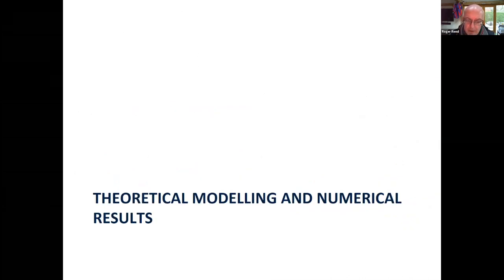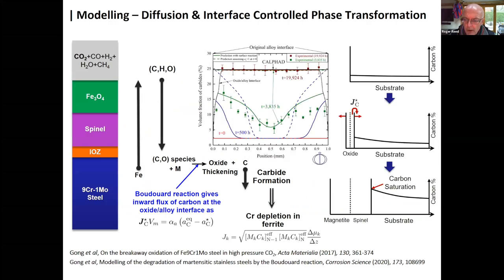Okay, so now I'm going to say something about some of the details of the theoretical model that we have put together for this project. So I'd like to start by just pointing out, of course, this is quite complex. You have a 9-chrome molybdenum steel, you have a spinel, and then a magnetite-based iron-rich spinel on top. Then you have this gas, which, of course, is quite complicated in its composition. And then we have a zone here where we have the interfacial reaction.